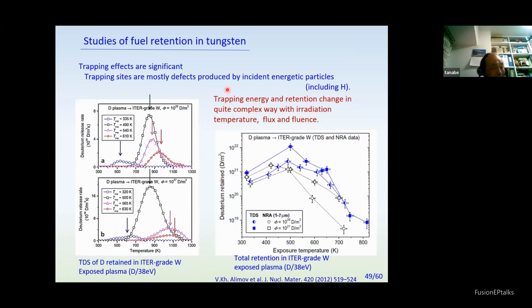In tungsten, it's a little bit complicated because the temperature dependence is not so simple. Irradiation temperature of 500 degrees gives the highest retention. This is due to the trapping effect because various different kinds of defects form depending on temperature, and retention changes. If there were no trapping, hydrogen retention should go down with temperature this way. So in case of tungsten, defect trapping is significant.